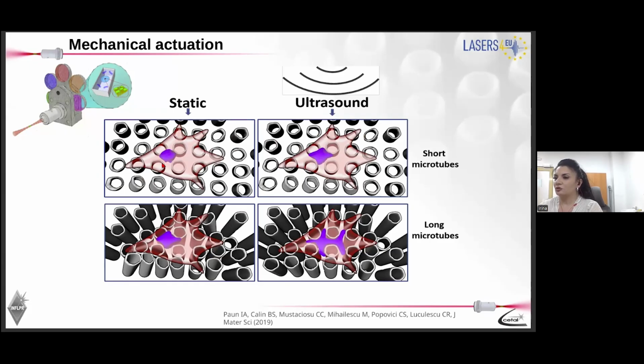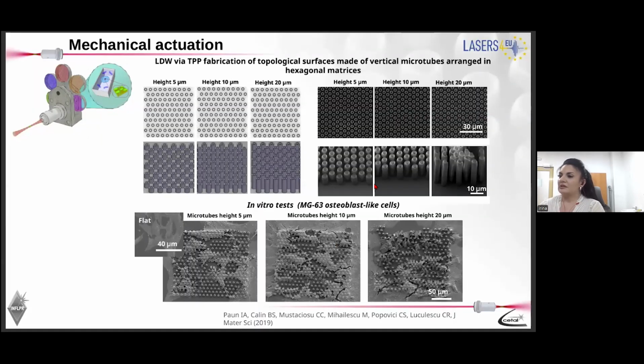In static conditions, normally the cell nucleus has an almost spherical shape. In contrast, on the highest microtubes that are also ultrasonicated, so they are submitted to mechanical motion, you see here a strong deformation of the cell nuclei. This is also what we monitor in our experiment.